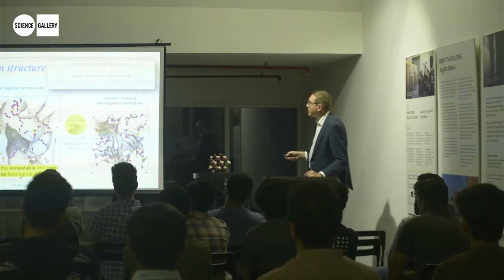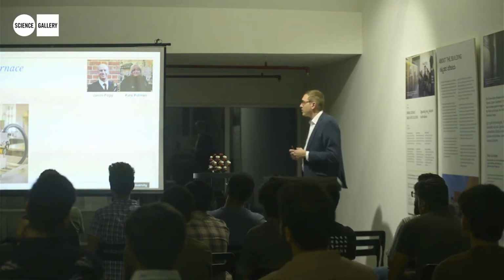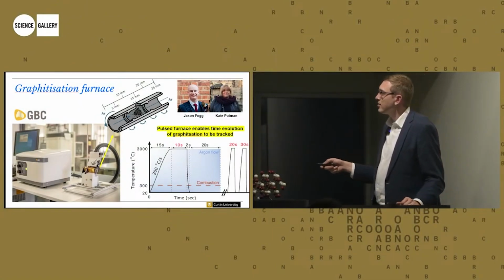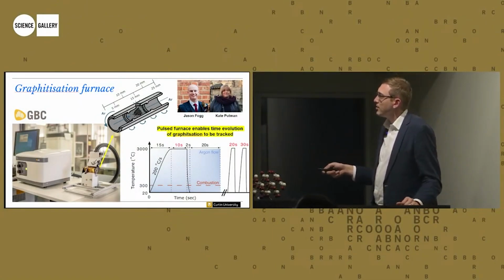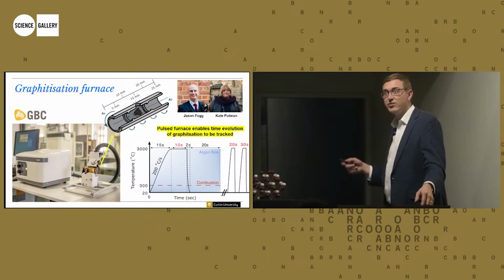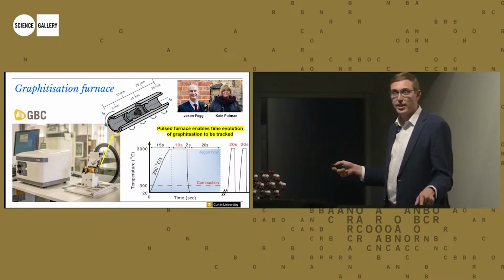Around this time, I went looking for these screw defects inside of different materials, and it was hard to look at them in the disordered carbons. But at this time, Jason Fogg and Kate Putman had been doing X-ray diffraction, but also heating of graphite inside of a custom furnace that was developed. It's literally about the size of your thumb, and it can heat material up to 3,000 degrees in a second. It's very unique because, as I mentioned, the furnaces used industrially take a whole day. And even a lab-scale furnace usually takes at least 2 hours to heat up to 3,000 degrees. So this is very fast. Little tube, and we can heat up to 3,000 degrees. We usually take about 15 seconds, but we can go pretty fast.